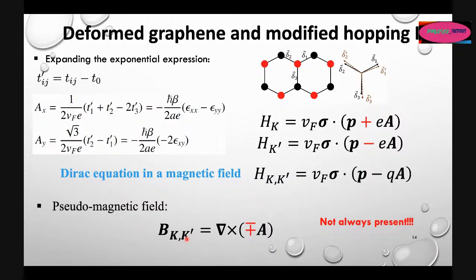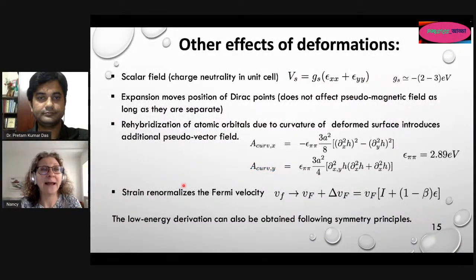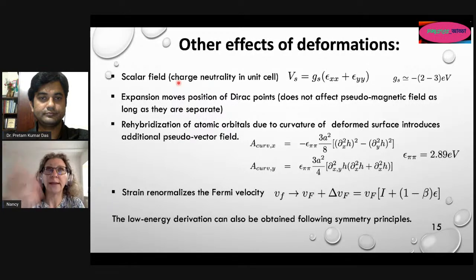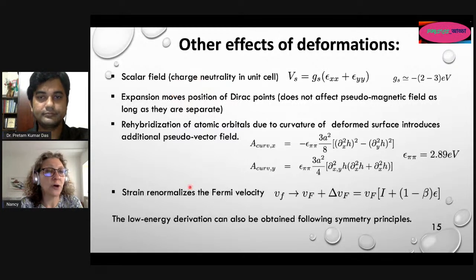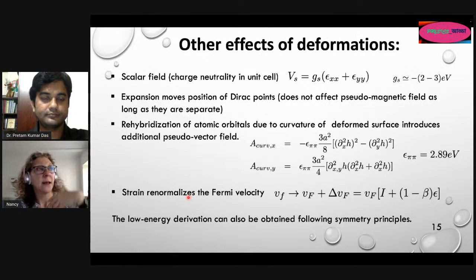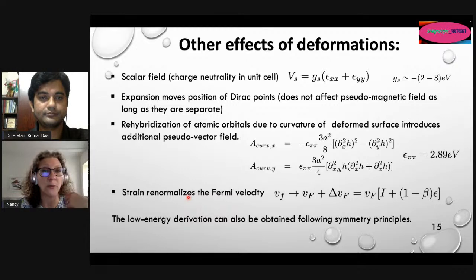So the fact that all these mathematical transformations, and it may seem like tricks many times, allow us to create this connection facilitates a lot our interpretation of measurements. So here I listed many other changes that the strain introduces, and that I will not go in detail because I checked the time. I am running late already, but I just wanted to let you know that the effect of a magnetic field appearing as representative of the strain is not the only effect. There are other effects that also modify the electron dynamics, and in a given situation you have to evaluate how important they are with respect to the presence of the pseudomagnetic field.